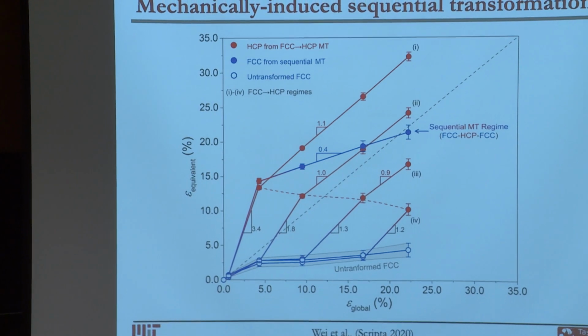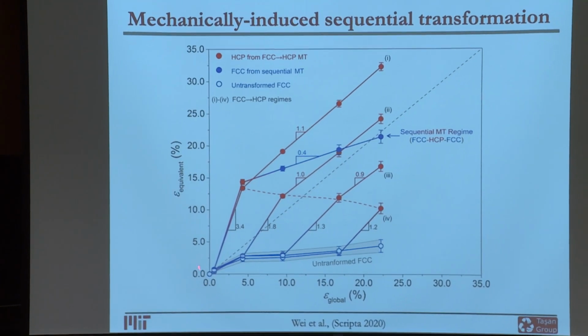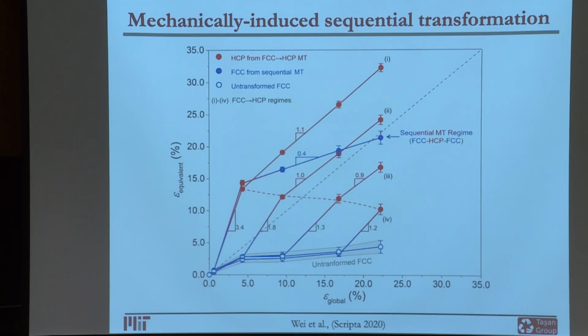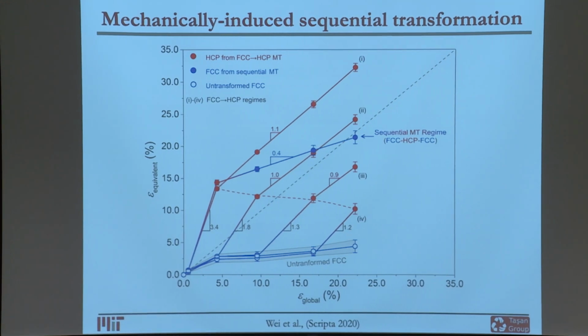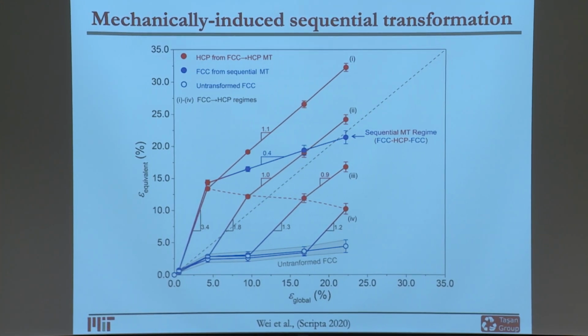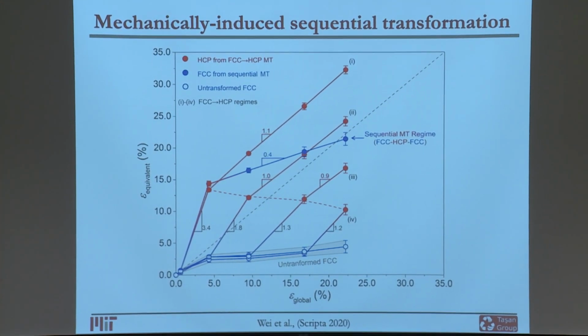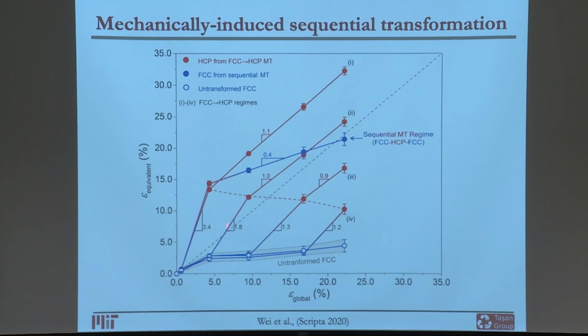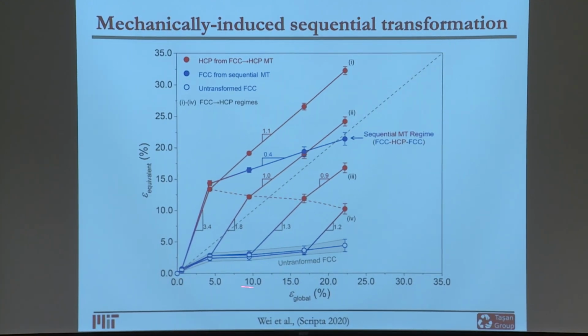And the key point about this new transformation, this is a very busy graph, but I wanted to share with you anyway, because you can form a new phase, but if that phase is not deforming or that transformation is not accommodating strain, maybe that's not so useful for you. And this plot essentially shows that when you plot average strains to local strains, this region that exhibits the double transformation both accommodates strain during the transformation, but also during the further deformation.